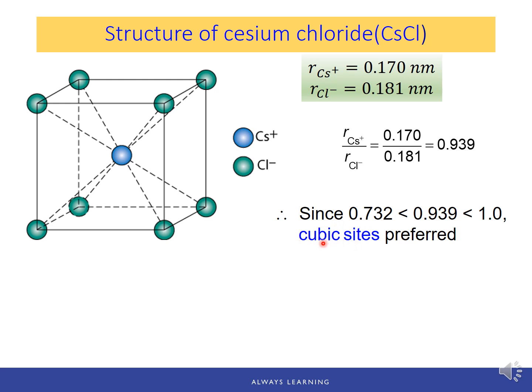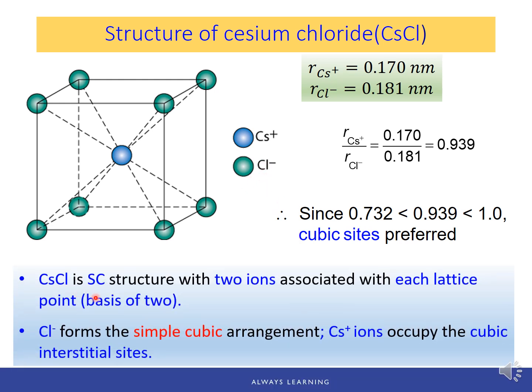Therefore, the cubic sites are preferred, which means the cesium cation will enter into the cubic sites, at the center of the cube formed by the chlorine ions. So cesium chloride is a simple cubic structure with 2 ions associated with each lattice point. Again, this is not a body-centered cube, but a simple cube. The chlorine ions form the simple cube arrangement, and the cesium ion occupies the cubic interstitial sites. So the coordination number for both ions is 8.